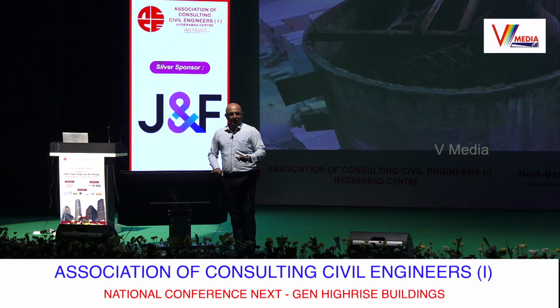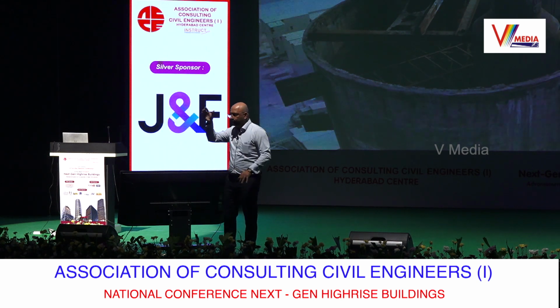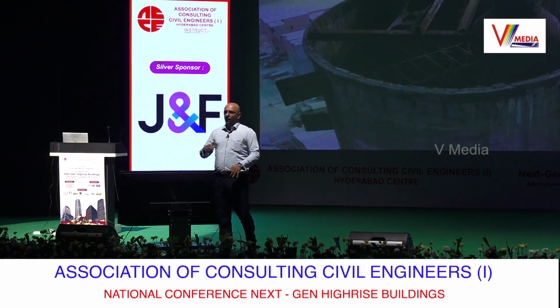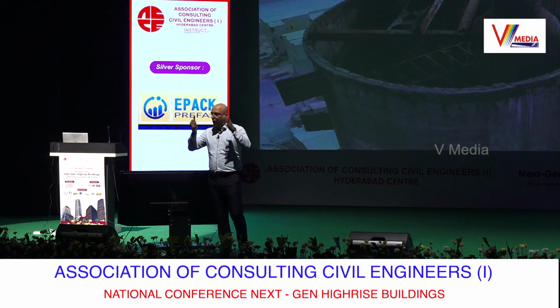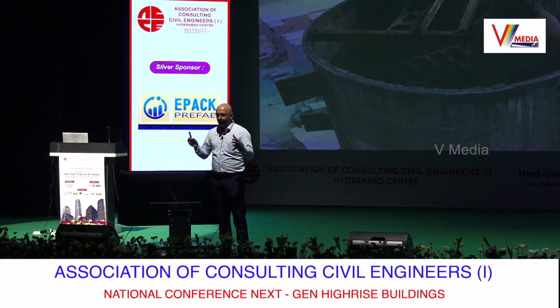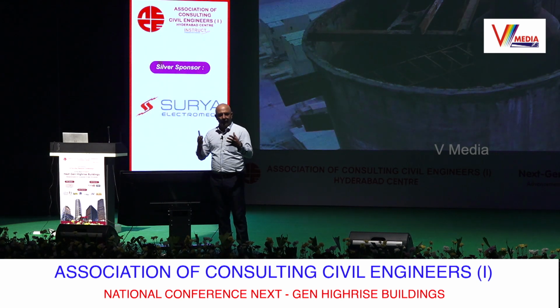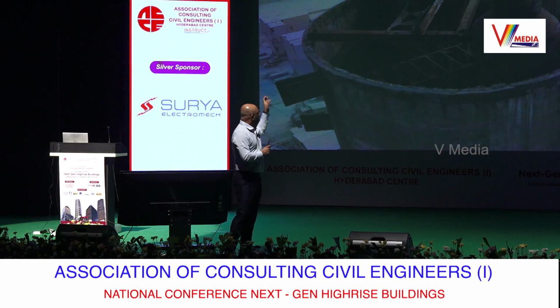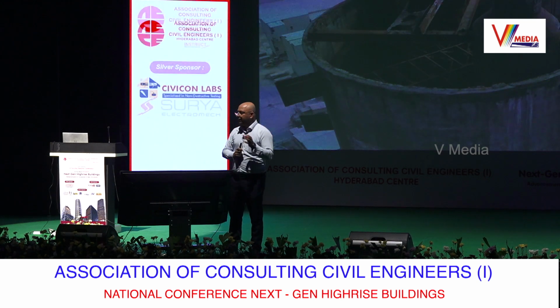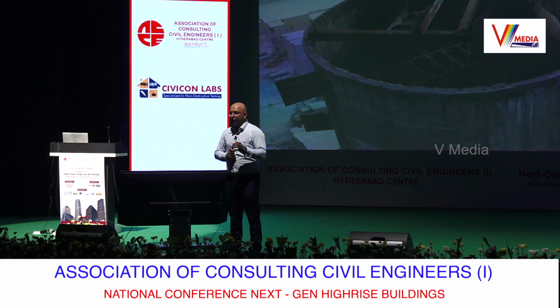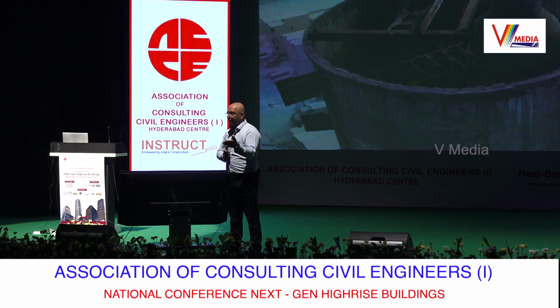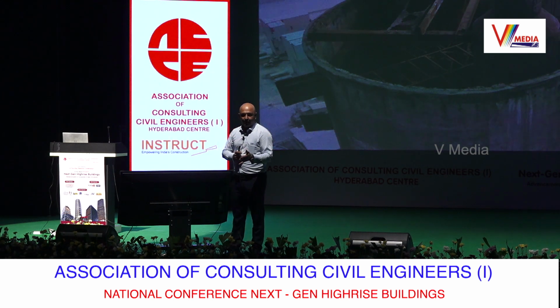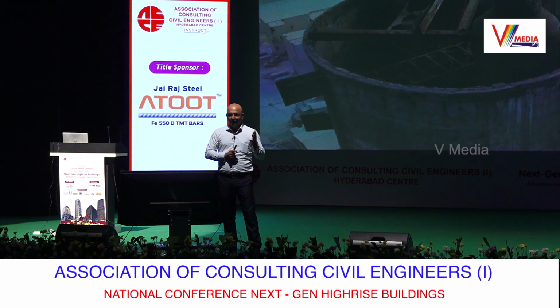The diameter of this is 4 meter, and the internal platform supporting the steel stack also had collapsed. So we had no access to this, so we used drones to check the structure, and we found out that the concrete on the top portion was badly damaged. I'll tell you why it was damaged when we go through the presentation. The steel stack thickness at many places had reduced from almost 16 mm plate to even 1 or 2 mm, and some places it had gone through.